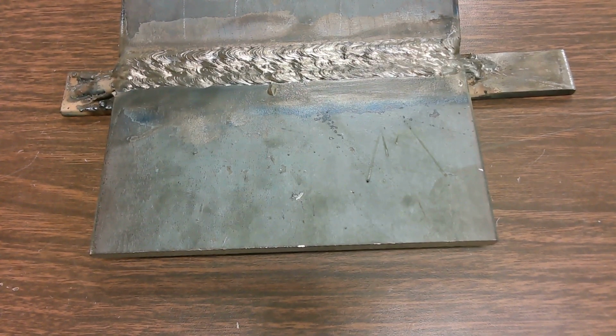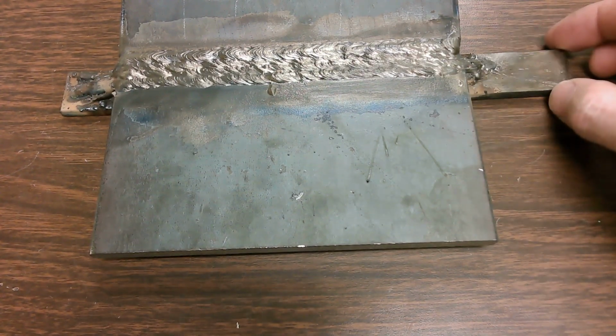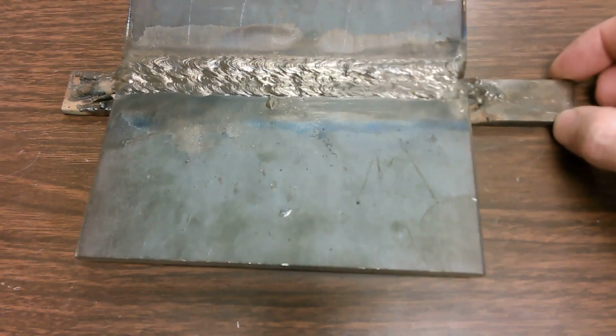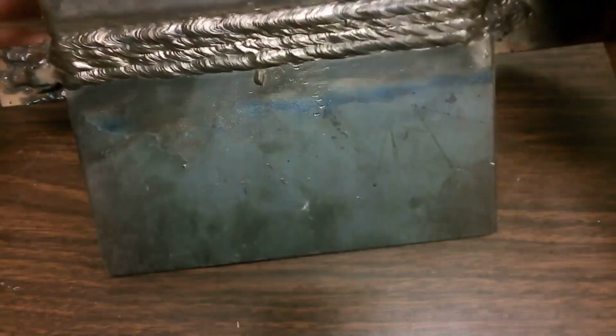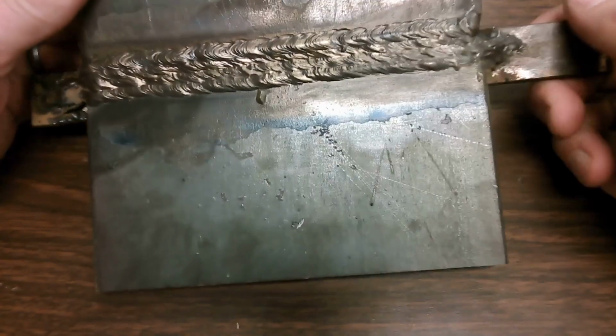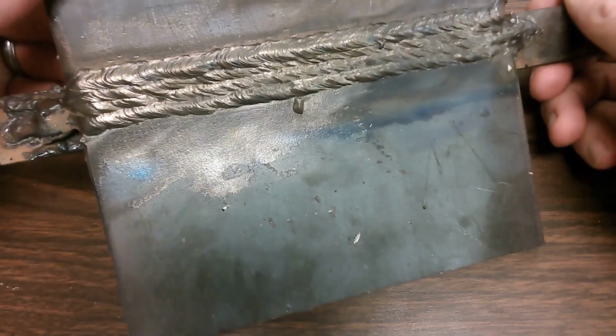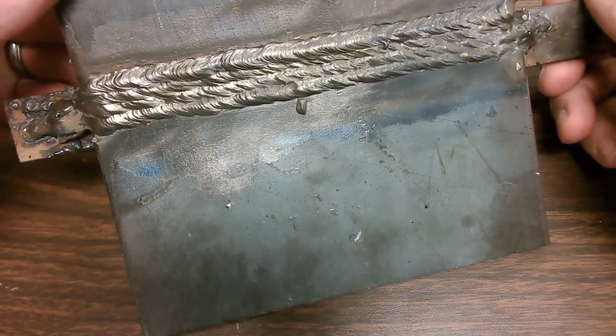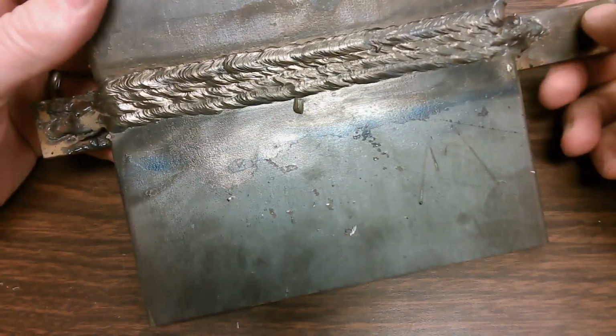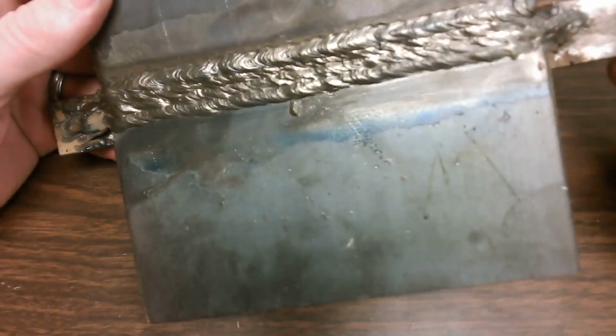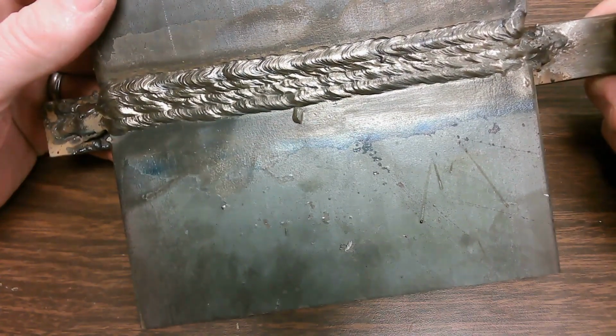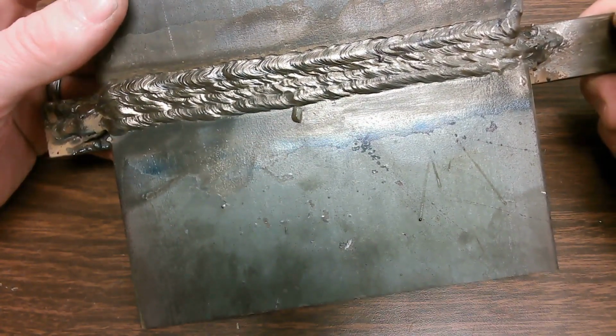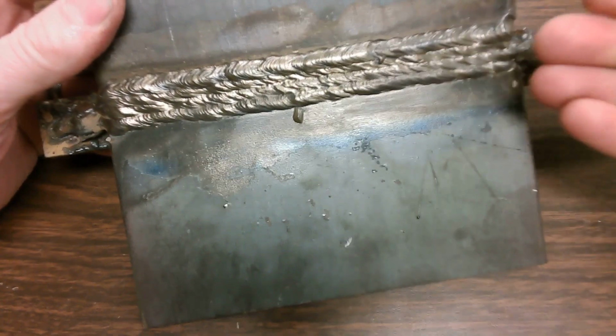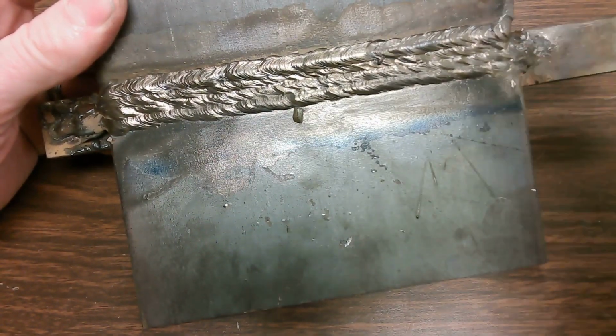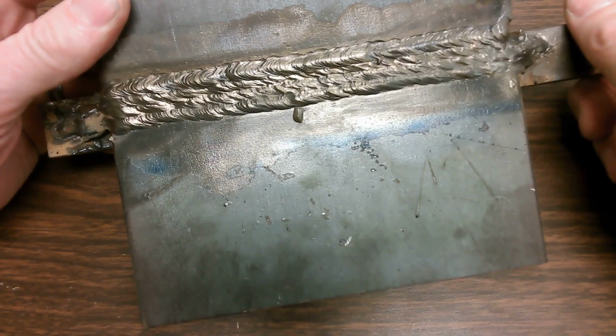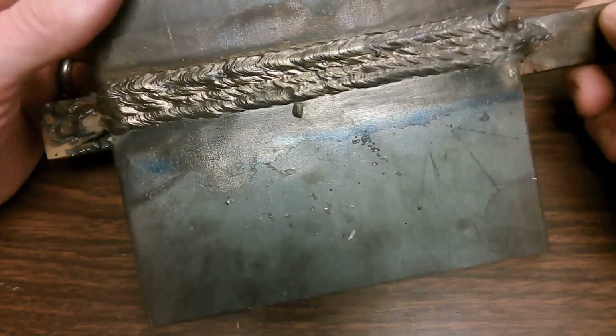All right, so we're going to start with some basic weld inspection from this 2G weld. The first thing I do when I look at a plate a student gives me is look at the weld in general, look at the shape of the beads, and look for any potential problems of lack of fusion, or any potential areas of underfill where they just didn't have enough reinforcement out on top, if it was still subsurface below the base metal. In general, this one looks fairly decent.